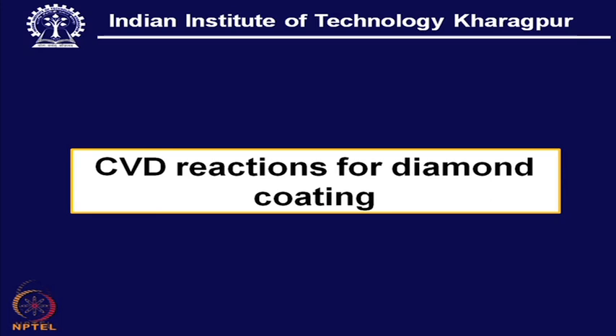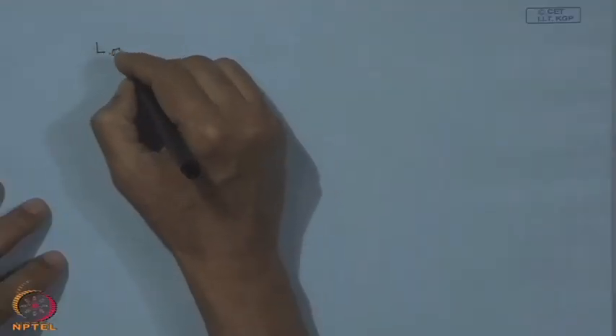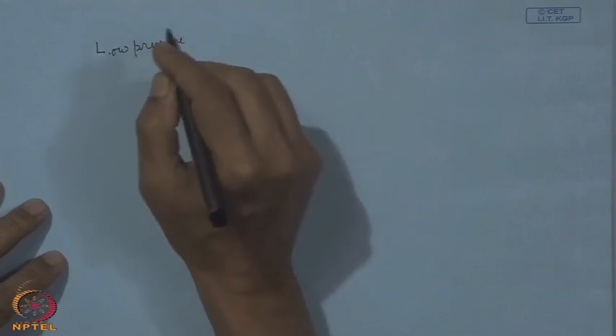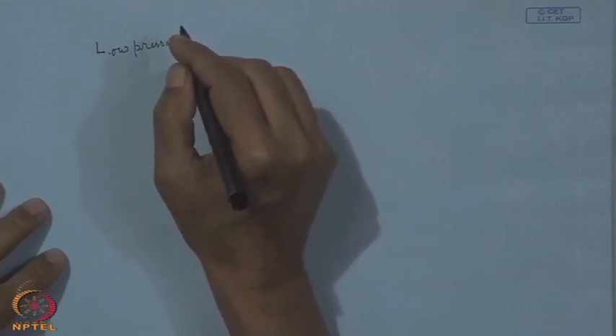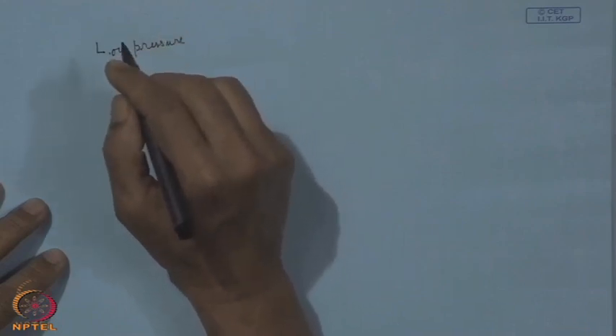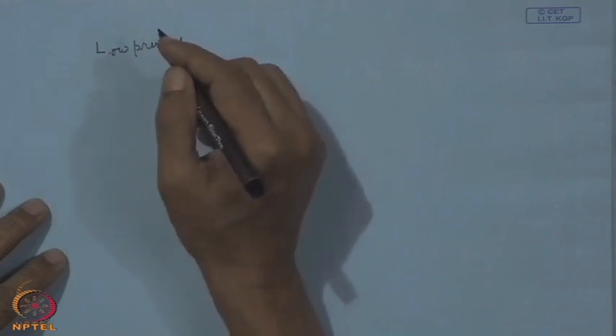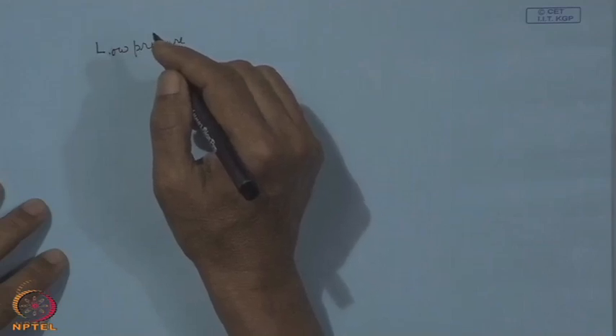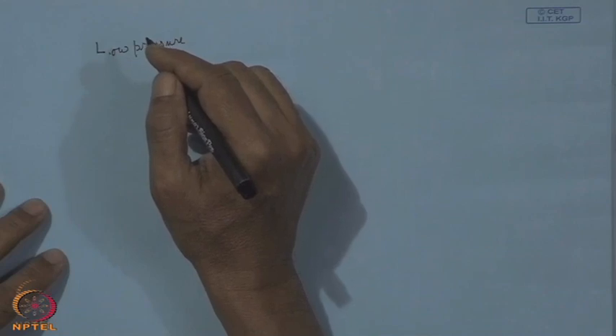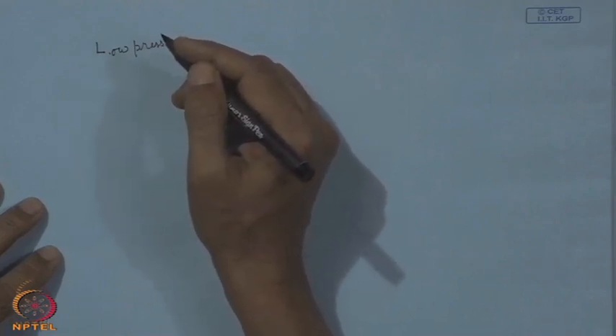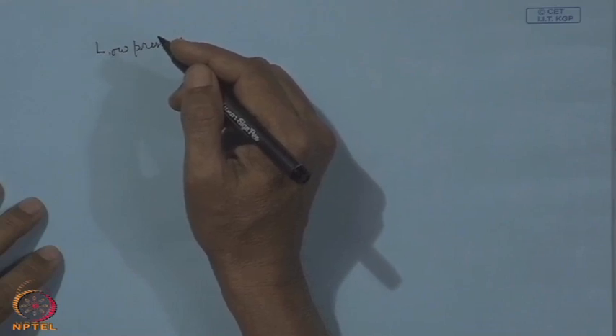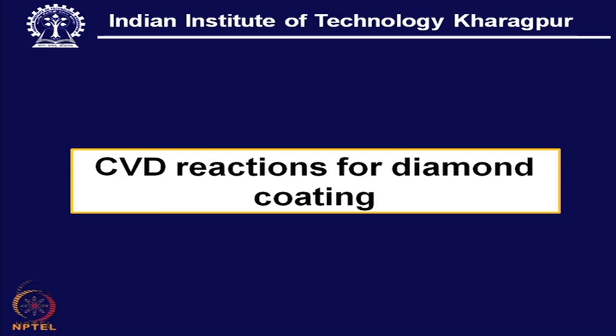Now comes the CVD reactions for diamond coating. One thing very important to know here is that in this low pressure synthesis, to accelerate the process or to make the process reliable, that means to reproducibly obtain this diamond coating over the substrate, one would like to have, at the very initiation, high density nucleation, and that should be augmented by some mechanism. This is exactly what we need here, the diamond dust or diamond seed, and that we are going to also discuss.